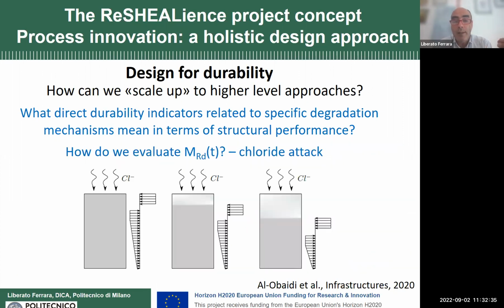But then in this, we wanted to implement mechanisms of degradation. And so we said, okay, what if the chlorides penetrate or the sulfates attack our cross section? Well, we will start losing material. This was a very, very severe assumption that we made. In the beginning, we did not have data, so we felt confident in using that. And we said, okay, let's simply remove the attacked layer, so we will have a reduced cross section. It's basically what we do when we perform fire design with concrete, fire design with timber, and so on.